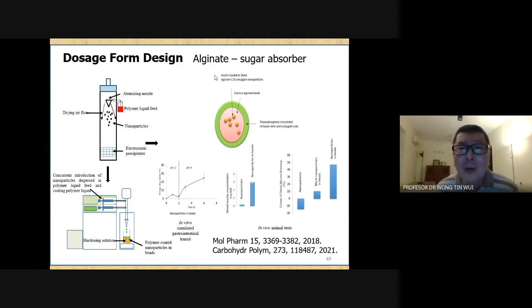They will not release the insulin at all. So on this note, we synthesized an alginate carbon 18 conjugate and complexed the insulin with the alginate carbon 18 conjugate into nanoparticles. Now, these complex nanoparticles are better in the sense that they can reduce the release of insulin in the early part of the gastrointestinal tract, and at the same time, they can release when needed, commonly upon the enzyme digestion of the alginate, right? Now, in order to further protect the alginate insulin nanoparticles from early digestion by gastric acid, we embed the nanoparticles in calcium alginate beads. Note that this bead is made from calcium alginate, with the aim to introduce more alginate that can also at the same time absorb the sugar in the gastrointestinal tract. Now we further protect the beads with a coat, which is a tripolyphosphate cross-linked chitosan oleate conjugate.